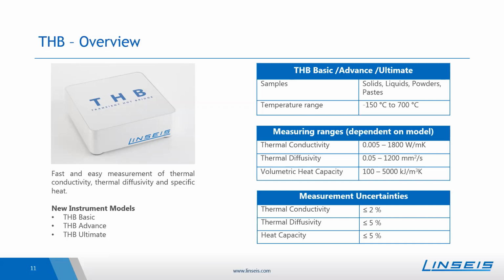The THB allows fast and easy measurements of the thermal conductivity and thermal diffusivity of materials, and by knowing the density, also the specific heat capacity can be determined. The THB allows the measurement also of solids, liquids, powders, and pastes, so it covers a very broad range of applications. The temperature range goes from minus 150 degrees Celsius to 700 degrees Celsius, so it also covers a lot of different applications.